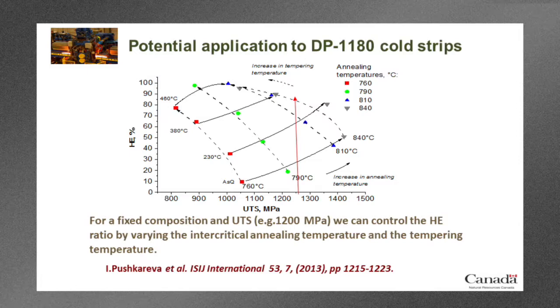So let's take an example. We want to make a dual phase 1180 steel. Then that would be positioned here along this red line. Depending on how we process that steel, from the same composition, we can have a hole expansion coefficient of about 20%, or we can go up to 80 or 90% just by varying the intercritical annealing temperature and the tempering temperature. So it's to show you that the final properties are very, very, very sensitive to these microstructural characteristics.